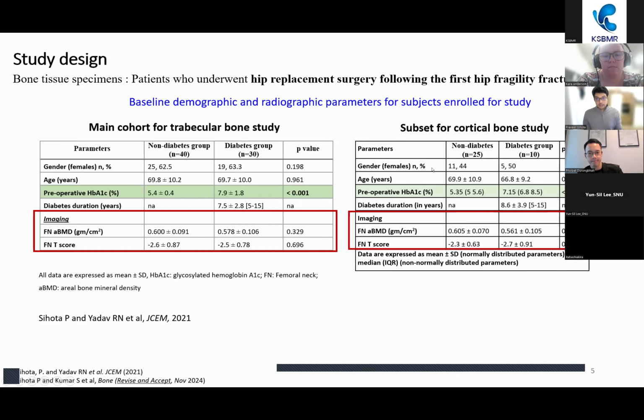A sub-study was done on cortical bone, where we included 25 cases from the non-diabetes group and 10 from the diabetes group. This subset comes from the main cohort, and the reason for the smaller number of bone samples is that we did not find intact cortical bone from the inferomedial region. That was the region of interest for the complete cohort, so the subset is studied here. Both studies are now accepted. One was published in 21 and another was recently accepted in the journal Bone.